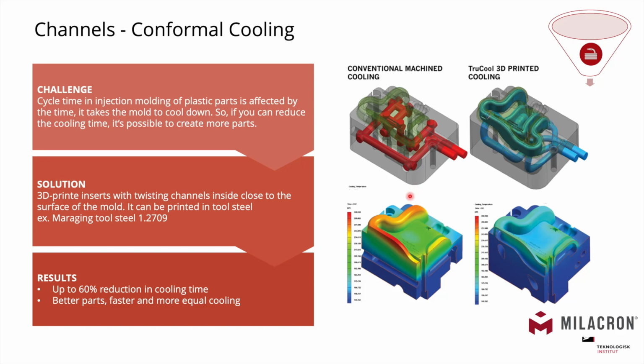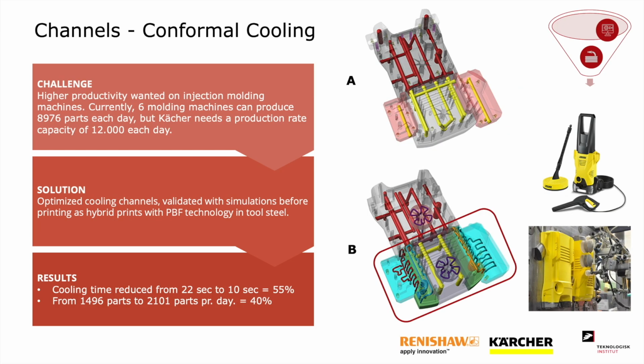But if we look at the cooling effect, we can see in the picture in the bottom left that the conventional mold has a much higher temperature than the 3D printed mold. This means that we can actually use the 3D printed mold to produce even more parts than was previously possible. This is also the focus of the next case, where we'll look a bit more in depth into how this is used in real life.